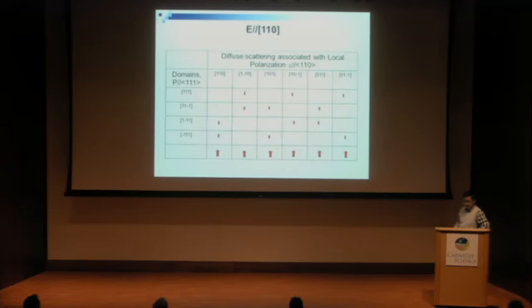And let's also see the field effect along the 110 direction. For the 110 field, we prefer 2 domains, along 111 and along 11-1, and don't like the other 2 domains which are perpendicular to the field. In this case, the diffuse scattering from 1-10 polarization will have 2 sources, and will be enhanced, and the diffuse scattering from polarization along the 110 direction has no source, and will be suppressed. And all other 4 still have an average contribution, so they will stay almost the same.